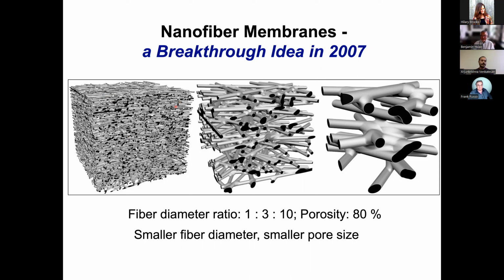And the value of this membrane would increase by orders of magnitude because you can filter a much smaller size. In principle, you can do this. If you have a technique or process, you can divide this fiber diameter by a factor of 10 or so. Then you can make nanoscale membranes.